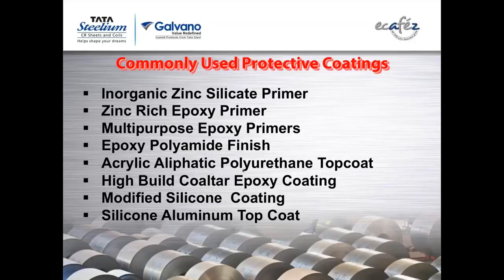Then high build coal tar epoxy. Usually coal tar will give you very good water resistance and it reacts well with epoxies also. This will give you a very good coating for things which are below the soil. So like pipelines and everything which are below the soil, we usually use high build coal tar epoxy. Modified silicone coatings are again used for high temperature resistance up to 250, 300. Silicone aluminum top coats we are using up to 538 degrees centigrade. Why 538? That is a direct conversion from 1000 degrees Fahrenheit to centigrade. So these types of coatings are used.